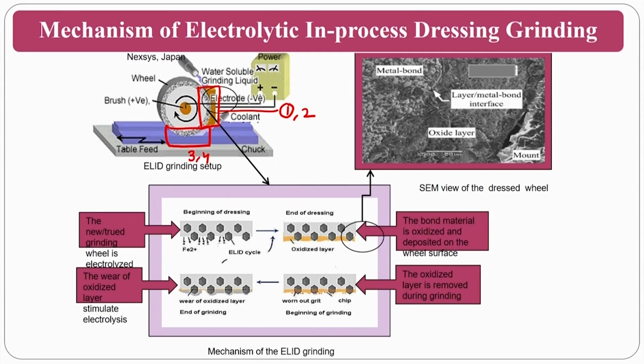Okay. So you can also see here stage 2, which is most crucial, where you have metallic bonding, a metal bond interface, and an oxide layer is formed. This particular oxide layer will start to wear out at the beginning of the grinding, and at the end of the grinding this will be removed, and the abrasive action will take place, and the material removal will be taken care of. Okay, this helps in avoiding wheel loading. Okay, as you know, wheel loading is a big problem whenever you are grinding soft materials and other things. For that purpose, you can use this in-process dressing process for the grinding.